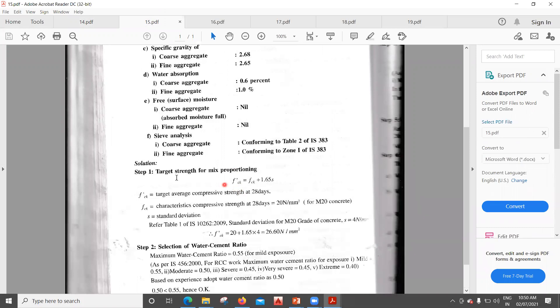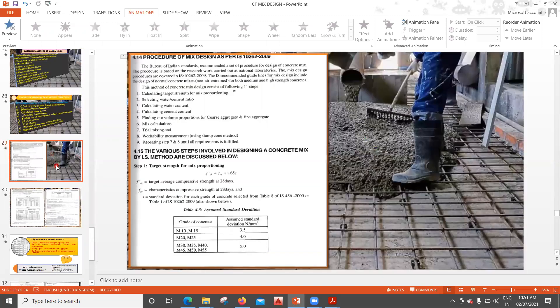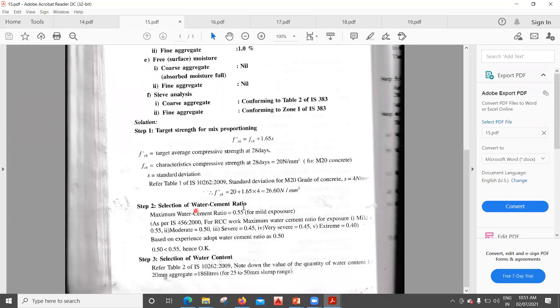As usual, we go for target strength for mix proportioning: f'ck = fck + 1.65 × s. For M20 grade, f'ck = 20 + 1.65 × 4. The standard deviation is 4 because from the table, M20 falls in the category where the assumed standard deviation is 4.0. This gives us 26.60 MPa.